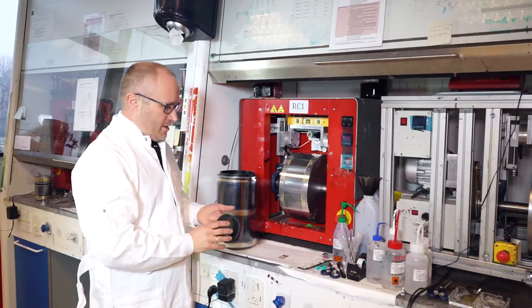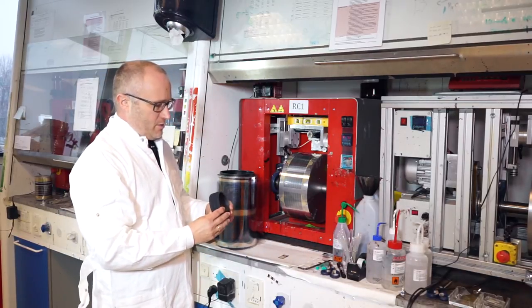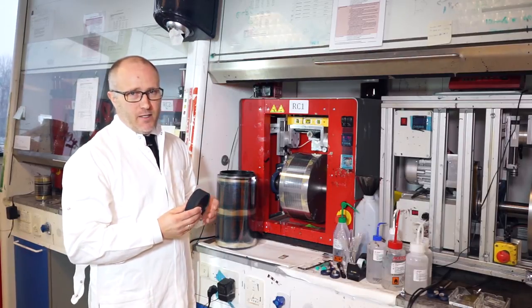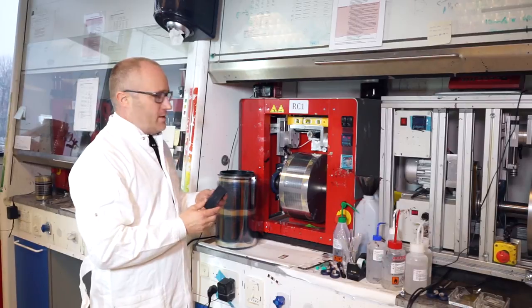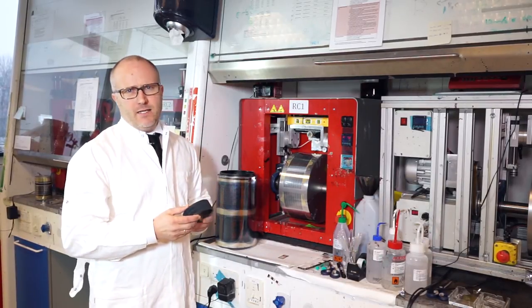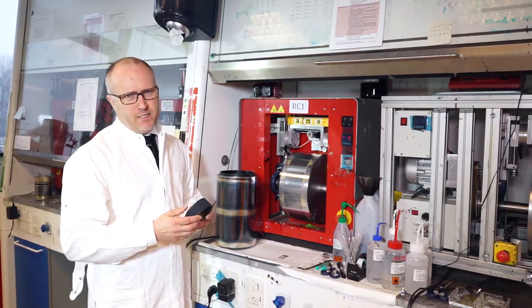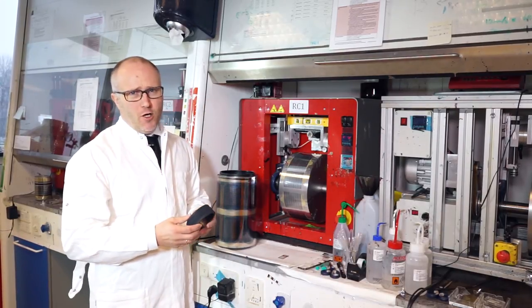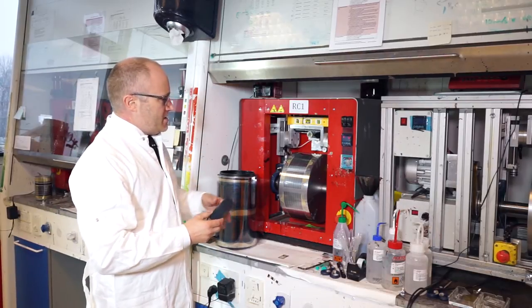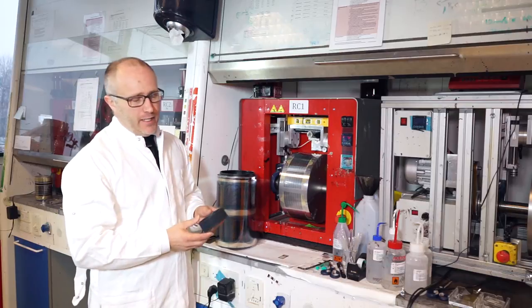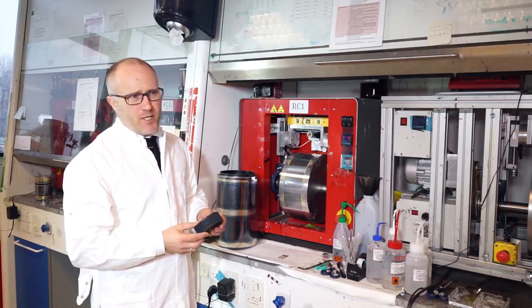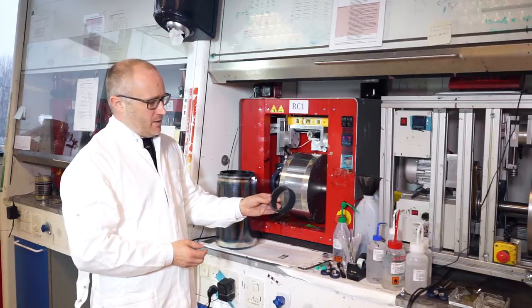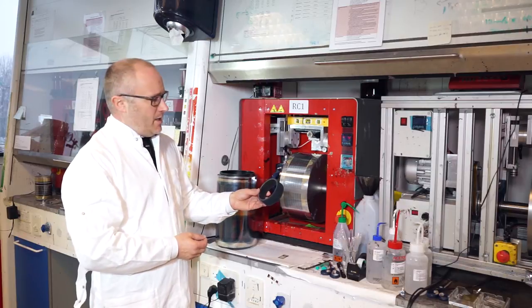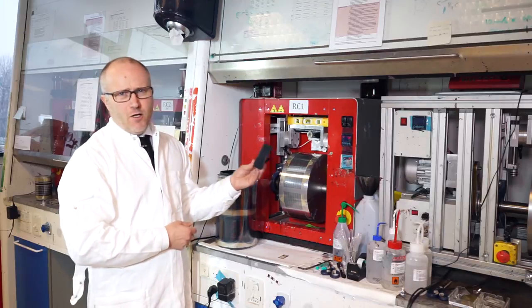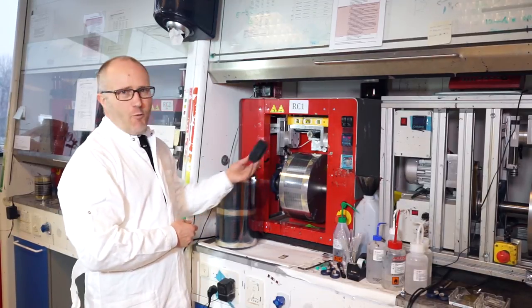But the most important development was a very simple flexo-like printing system that enables us to print metallic or metal paste back electrodes, typically silver paste formulations. It can be either thermally cured or UV cured silver paste formulations. Since the roll here is only 1 meter long, it allows a very simple flexo operation where you just load this roller. This is a typical piece of a flexo sleeve from a professional flexo machine. You just load this with silver, and you have just enough silver on this stencil to coat 1 meter, and then you have to reload.